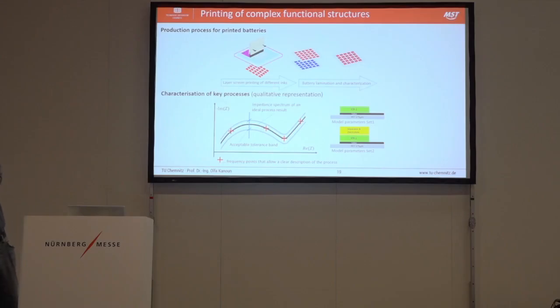capacitive structure. We measure in our laboratory the so-called golden sample. We have an ideal product, and we measure this electrical characteristic from this golden sample. Later on, we can go into the production process, even in this huge matrix with a lot of points, and we compare at the end the impedance spectra with the golden sample. So this is quickly done. This gray curve is a tolerance band around the ideal curve, which is maybe acceptable.